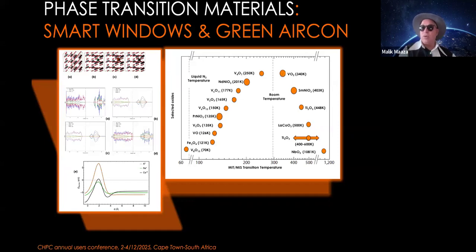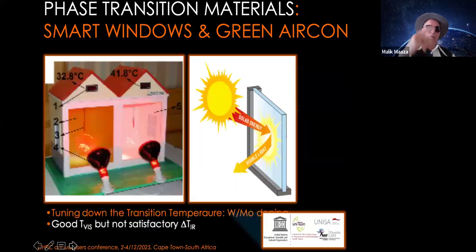So we are looking for this material, but we have to modify it. So how can we do it? We have to go for data mining, machine learning, artificial intelligence, and molecular dynamics, density functional theory, and so on. And you find out that instead of using thick VO2 films, it's better to use thin ones and so on. And when you do that, you are able to find the ideal coating. And that ideal coating, as you can see in this toy house, shows the house with the window without coating, and this one is the same one but with the coating, the orange coating, as you can see.